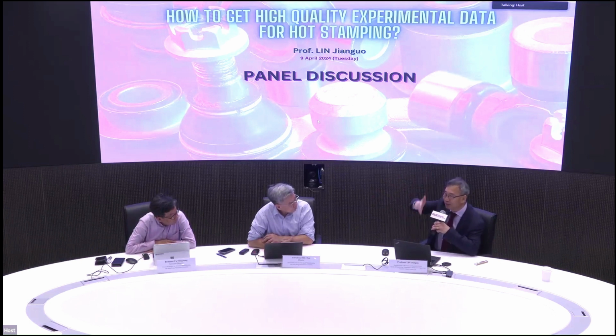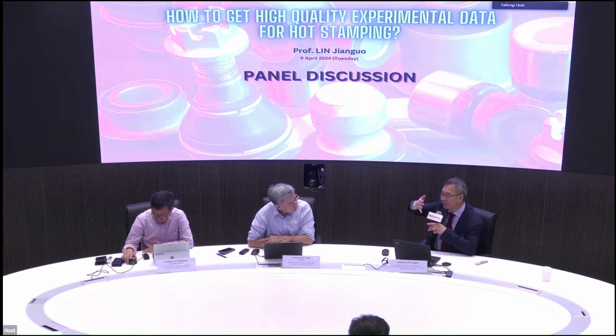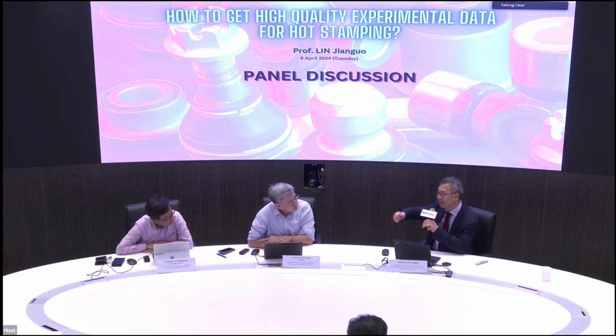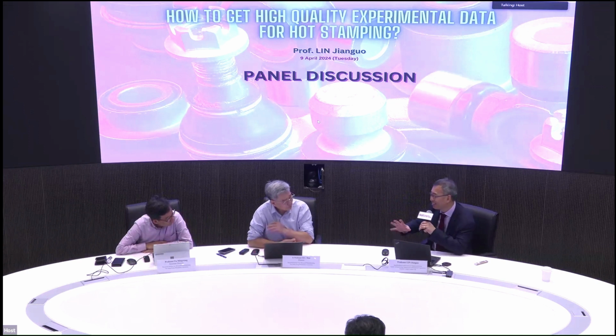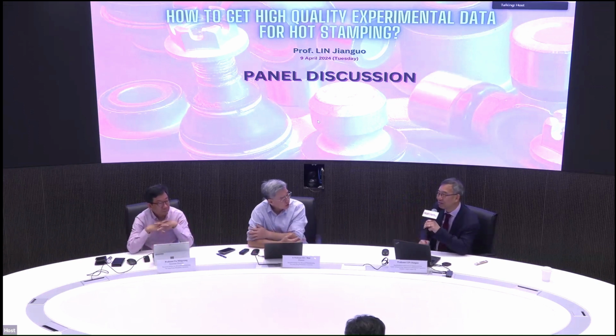But considering dislocations, various things, and the forming process, we need to control the cooling rate at about 50 or 60 degrees per second, so that we have time to do the deformation. If the deformation takes too long, we will enter the C curve, and the material becomes bainite or pearlite. Then the data is not valid anymore. It's a bit complex. We need to control the phases of the material. You try to form it still in austenite.